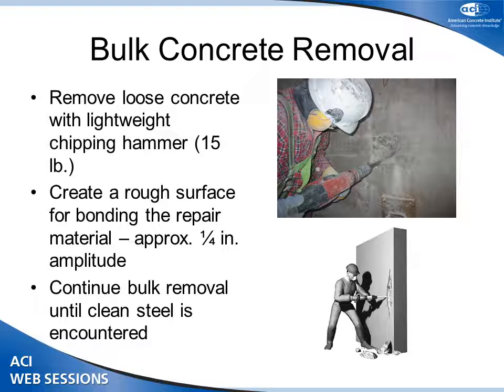In some cases, you want to continue the bulk removal until you start to get into clean steel. If this is a corrosion-related repair, that would be a preferred method, is to expand the area of the repair outside of active corrosion, or in some cases, the engineers will limit the area of the repair by marking out the deteriorated area only. And there you see the bulk concrete removal in process.